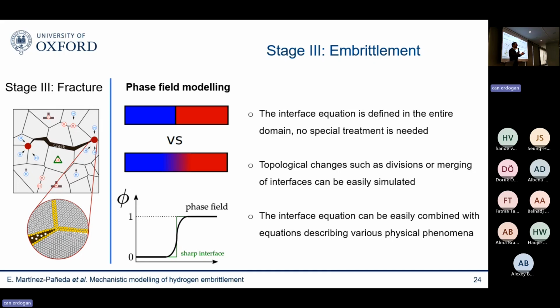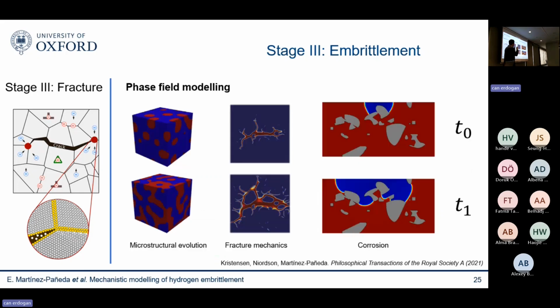Topological changes such as divisions or merging of interfaces like crack coalescence, crack branching, those are naturally captured without any ad hoc treatment. And then finally, it's very well suited for multiphysics problems because you can combine this crack equation with any other equation that you're interested in, hydrogen transport, uptake, whatever you care about. And I mean, phase field modeling, as I used to say, has really been a revolution in many areas of science and engineering. It all started in microstructural evolution, what is now by far the most widely used technique to simulate solidification. We're interested in its application to fracture mechanics, but again, it's becoming very quickly the dominant technique.